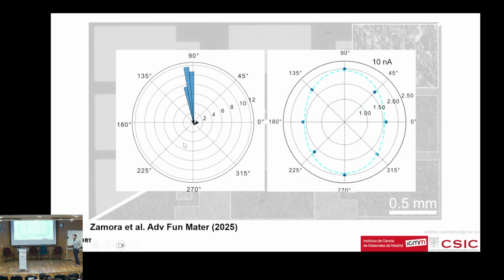And then when you measure electrical transport properties, you see that indeed there is an enhanced current along this crystal direction and a depleted current along this direction, because all these flakes are aligned along the same direction. And this is interesting because basically this film is inheriting this anisotropy of the bulk single crystal, okay? But this is not a single crystal. It is a network of interconnected flakes with a lot of flake-to-flake junctions in between, and still the overall device shows the same kind of anisotropy, okay?